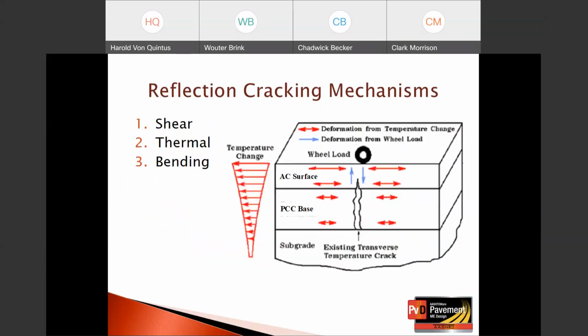Those 3 mechanisms are schematically illustrated in this slide. The 3 that we'll refer to are shear, thermal, and bending. Basically, when a wheel load goes across the location of a crack in the existing concrete or asphalt layer, there are differential deflections when the load goes across the crack. Those are related to shear in the asphalt overlay. There's also the bending as the load goes across the crack in the existing pavement, where we have increased tensile strains at the bottom of the asphalt overlay.